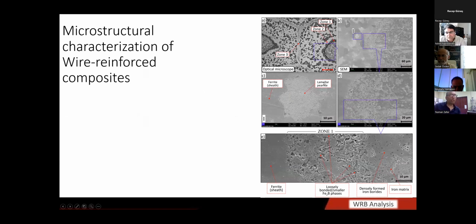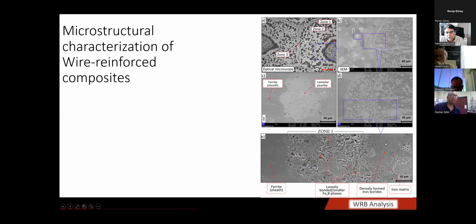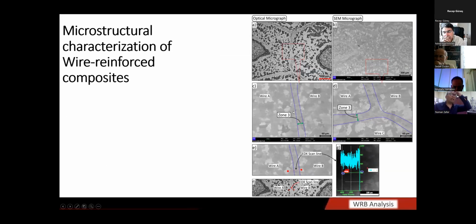We needed to see what is around the wire core and what is going on there. What we saw is that the iron boride phases have formed there, but they are loosely bonded and not as cohesive and dense as the iron boride phases in the core. The ferrite sheath, which was in contact with these cores, doesn't show any pearlite phase. Here is an interwire boundary region. They also show no pearlite phases, and only iron borides or only ferrite phases have formed. In the SEM micrograph, you can see it not very clearly, but in the optical micrograph, it is very clear.